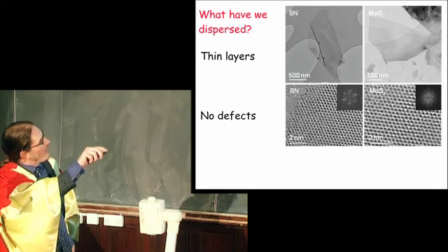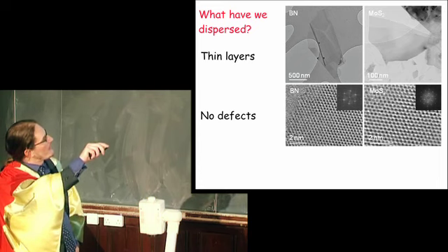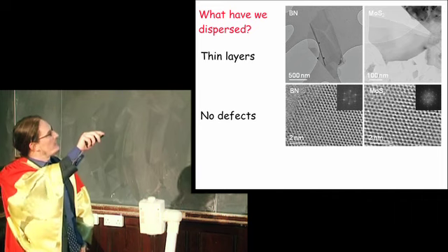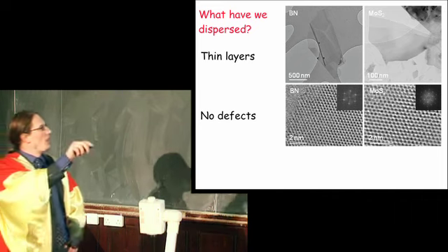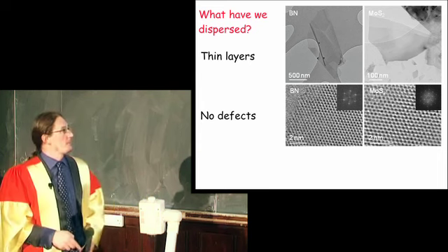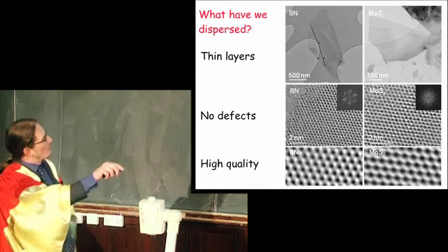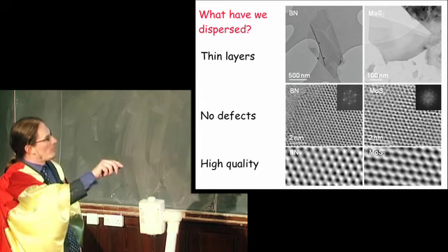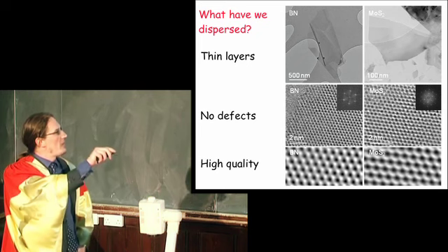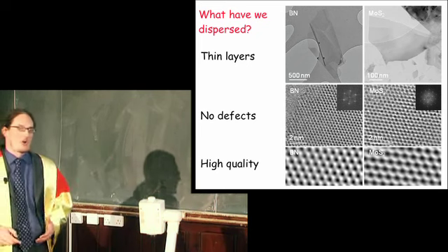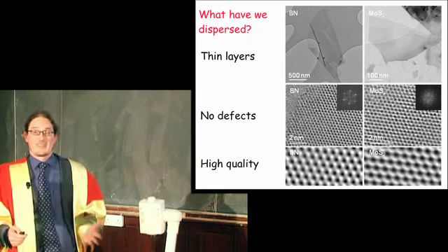These are effectively atoms, and you can see the atoms are arranged in a nice hexagonally symmetric pattern and are pretty much defect-free. And if you look even closer and do a little bit of filtering, you get almost perfect structure. These experimental images show structures that are almost identical to what you would see in a textbook.